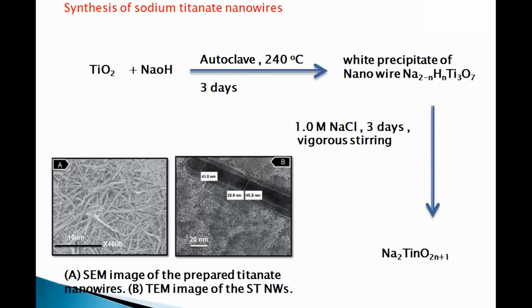The third step is synthesis of sodium titanate nanowires as a composite. We prepared them by adding titanium dioxide to sodium hydroxide, running in an autoclave at 240 degrees for 3 days. We produce a white precipitate of nanowires, followed by adding 1 molar sodium chloride for 3 days under vigorous stirring. And this is a picture showing the analysis of the sodium titanate nanowires.